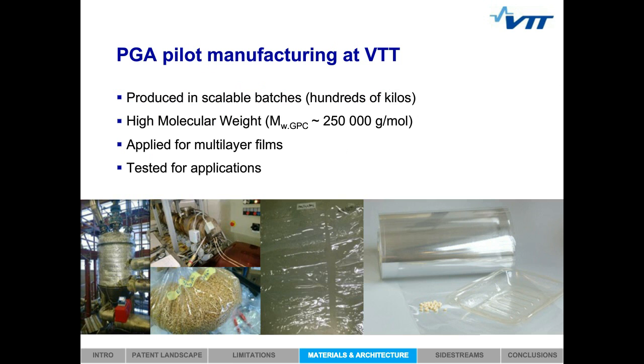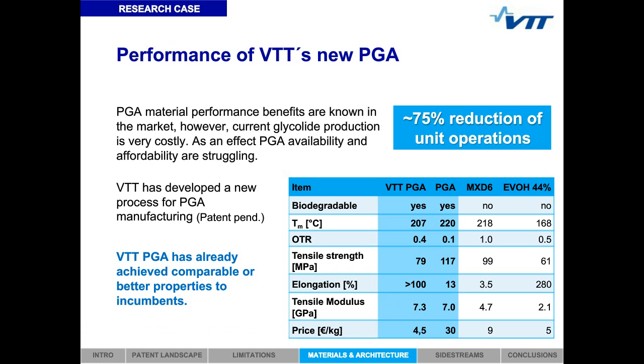VTT has already demonstrated this PGA production at hundreds of kilos scale. The material has very high molecular weight, 250,000 grams per mole. We have applied it for multi-layer films and tested in several different applications. Here we compare this VTT PGA with existing commercial PGA and also with some existing high-performing oxygen barrier materials that are commonly used in packaging applications.